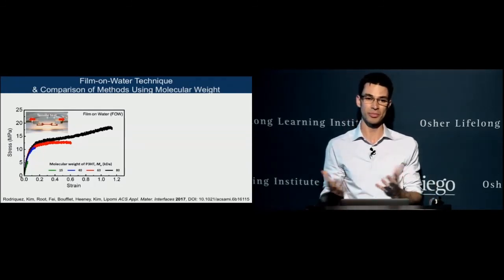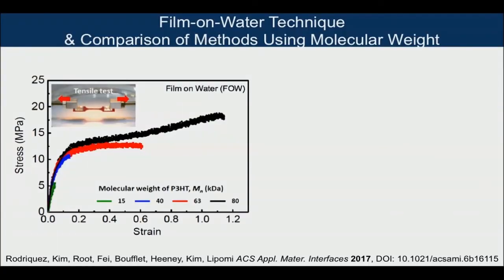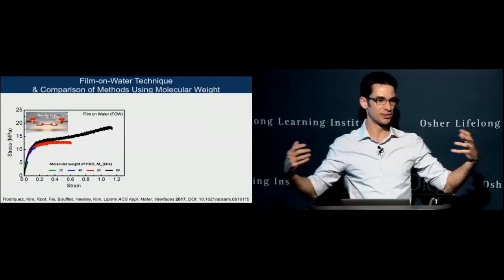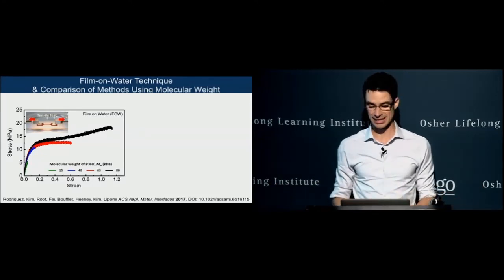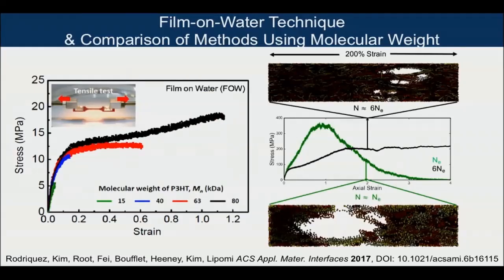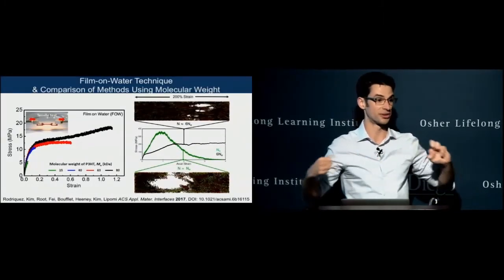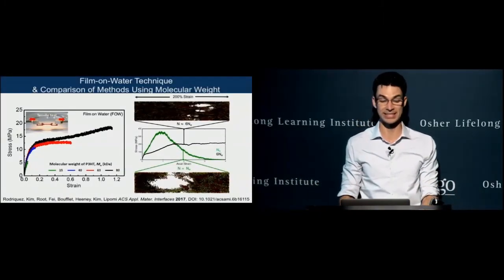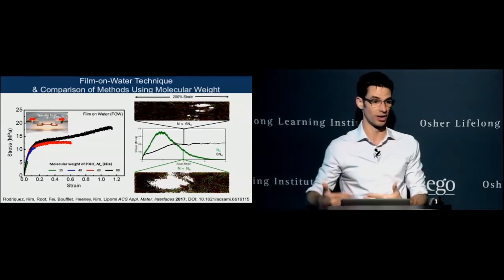One of them, and this is probably the simplest one, is just how long is this polymer chain? How long is this single molecule of plastic going to be, and what is that going to do for us technologically? Well, it turns out if you have super long strands of spaghetti, they tend to tangle up. So we call those entanglements, and we can use theory to calculate the entanglement density, which is on the right. So this is how many knots have kind of been formed in the material. And if you look on the left, if you go from green to blue to red to black, that is more entanglements, and you can stretch out the material even farther depending on how long the material is. And you can use the chemistry to tune how long the chains are going to be.